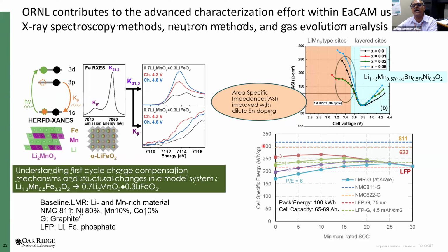They are much larger. No, I understand that. I'm talking about lithium transport, same as you were. So I'm trying to figure out what role the tin at the grain boundaries plays. Is it just that it caused the grain boundaries to exist, that it drove the system to make smaller and smaller domains that you see in the TEM? Or is it active somehow electrochemically? The tin by itself is not electrochemically active. This is purposely; we wanted to choose an element which is not electrochemically active.